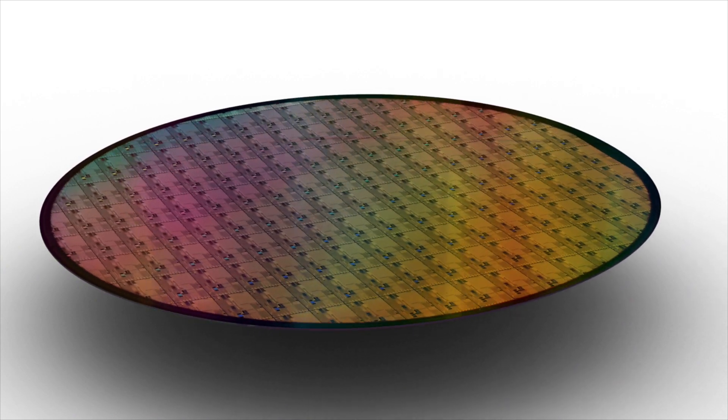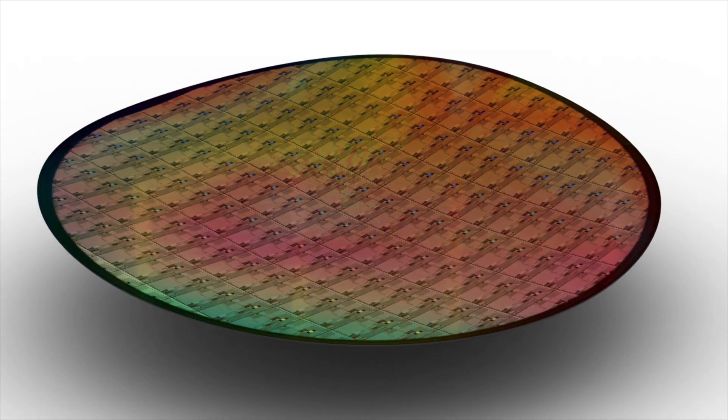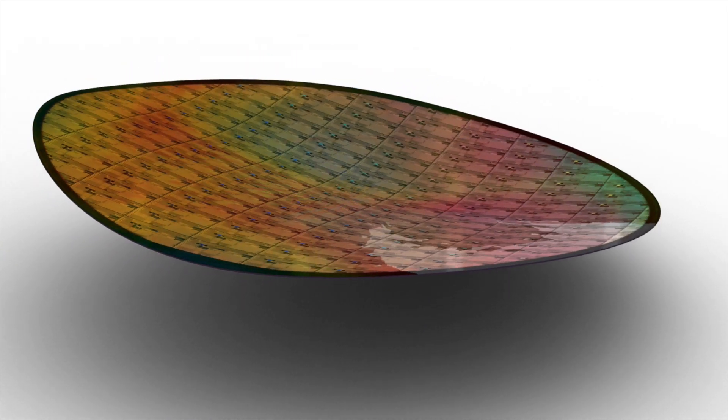If you look at fabrication of power devices such as IGBTs or MOSFETs, the process involves thinning down those power device wafers to far less than 100 microns to enable better heat dissipation and higher power densities. At these thicknesses, the device wafer is easily warped due to the high intrinsic stresses in the structure.